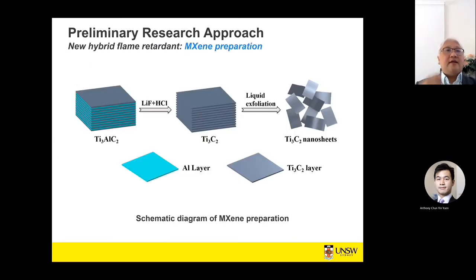The MXene that we've chosen here, in its raw form, is a titanium aluminum carbide. Through immersion in acidic solutions, the aluminum layers in between the titanium and carbide are etched out, and then it is exfoliated through liquid exfoliation, resulting in Ti3C2 nanosheets. And that is the 2D nanosheet that we will be using as a flame retardant in a layer-by-layer approach.